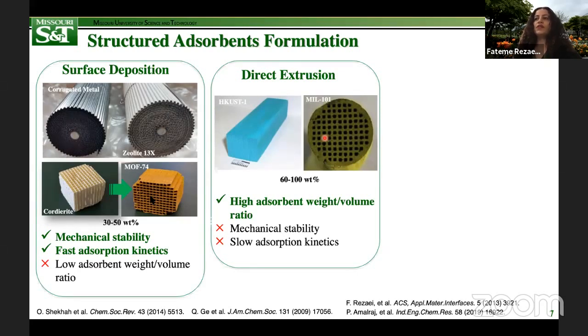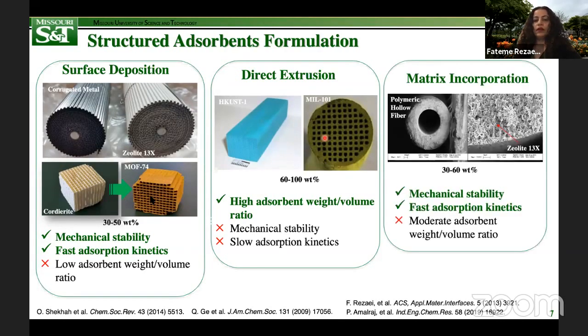Here, the properties of the formed structures are strongly dependent on the properties of the source adsorbent powder, of course, but also the surface tension and viscosity of the binder that could be used to shape these crystalline powders, and the interactions between them. Also, I should mention that mechanical stability is not as high as the monoliths or the structured adsorbents made by the first method. And sometimes we get slow adsorption kinetics, especially for the thick wall monolithic structures.